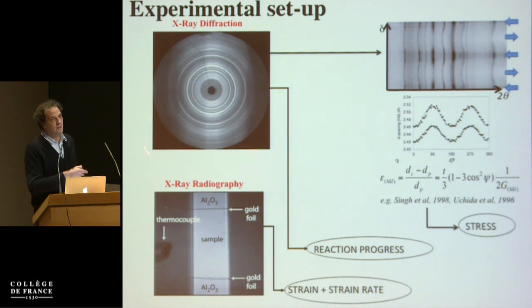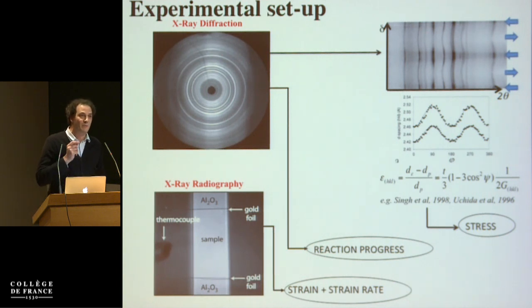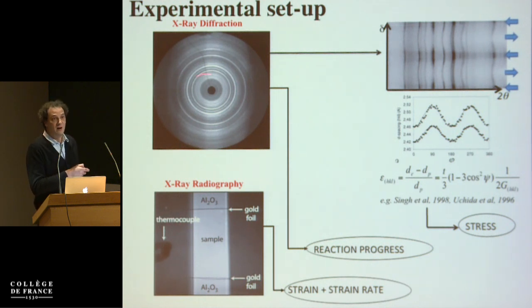And we also have the X-ray diffraction. So the X-ray diffraction gives us an idea of the mineralogy. So all these rings are called Debye rings, and they are linked to the lattice spacing in the minerals. And so we know what minerals are in the sample. But also, if you look at these rings and you unwrap them, you see that instead of becoming lines, they look wiggly, because that's telling you that the HKL spacing, or the lattice spacing, is different along the different directions you're looking at. So if you know the elastic parameters of your material, you can fit those wiggles by sinusoids, and then you can extract sigma 1 and sigma 3. So you can extract the stress. And so from the X-ray diffraction, you have the stress and the reaction progress. From the X-ray radiography, you have the strain and strain rate. So now you're more or less into a regular rock mechanics experiment.